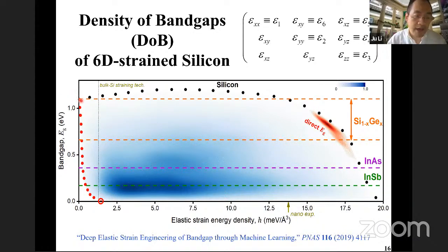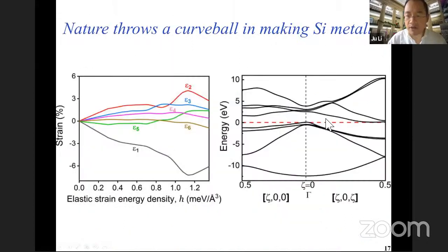And so without strain, silicon band gap is the well-known 1.1 electron volt. But if you're just willing to pay some strain energy density, you can make it into an infrared detector if you want. And in fact, this red dot is the sort of the most cost-efficient way to reduce silicon's band gap to the metallic state. And so this point is what we call the first metal of silicon. It is still an indirect metal.